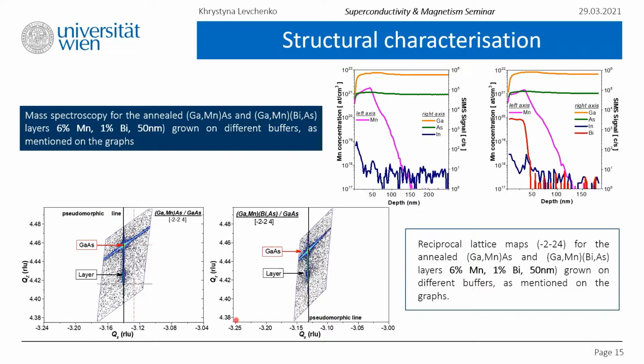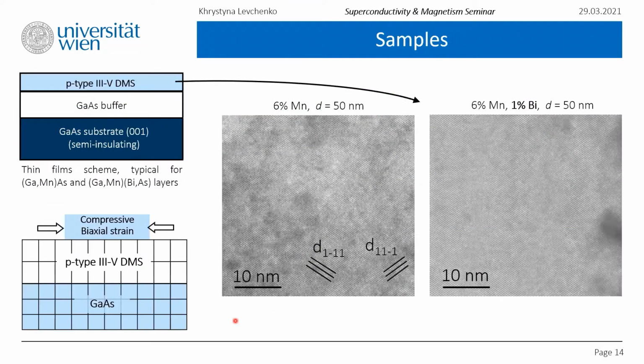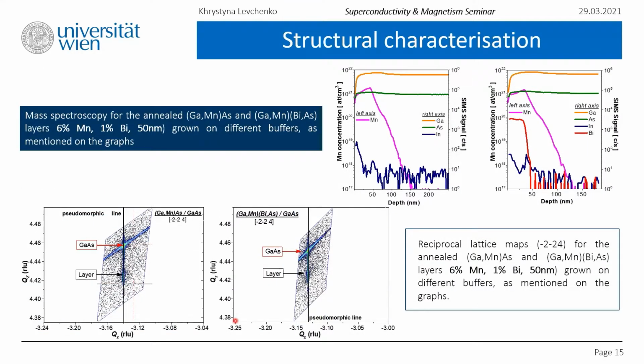The measurements were performed on the same set of samples, perhaps even the same samples, as in the previous transmission electron microscopy measurements. All the reciprocal maps show Bragg reflection peaks from the corresponding layers. They are all visible. The sharpest one, the most distinct one, obviously belongs to the substrate. It's colored in red. And the broader one originates from either the ternary or quaternary compound. Also, they lie on the same line, meaning that the lattice in-plane parameter fitting of the upper film with respect to the one below is quite good.